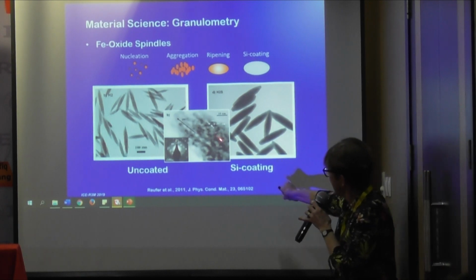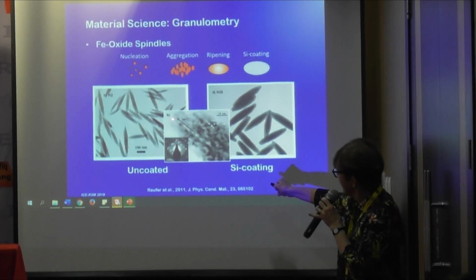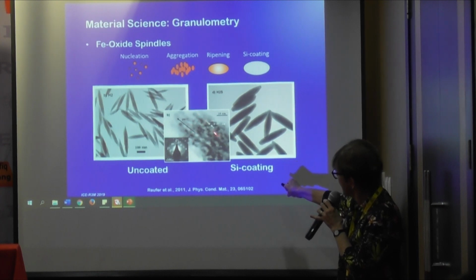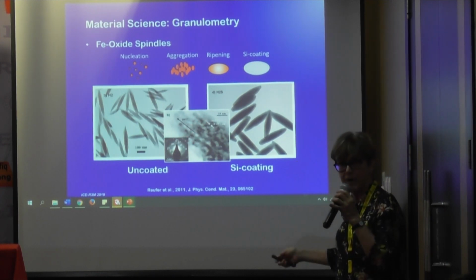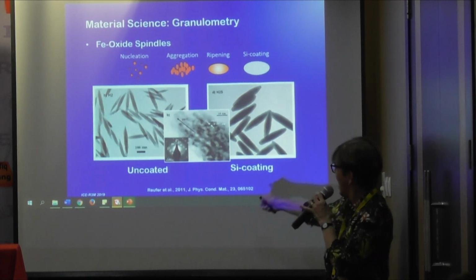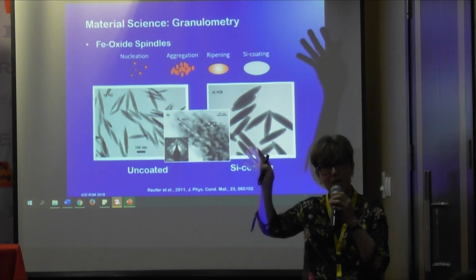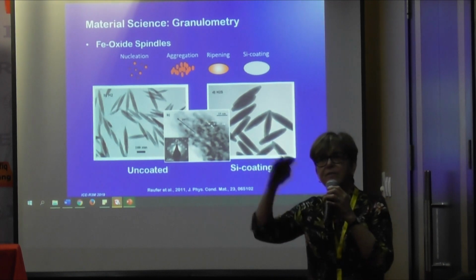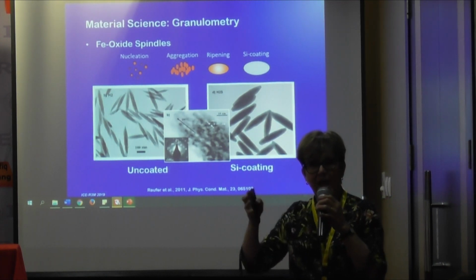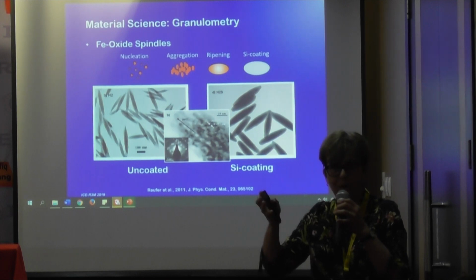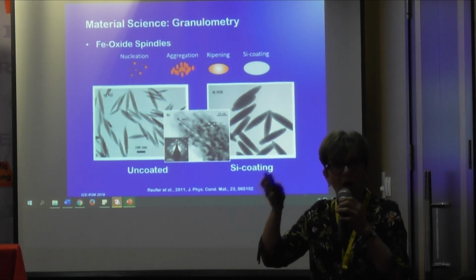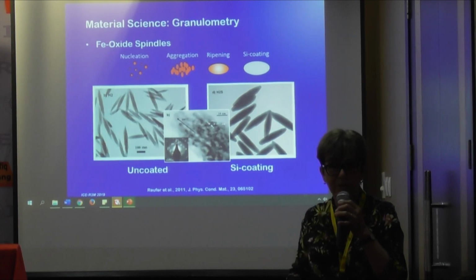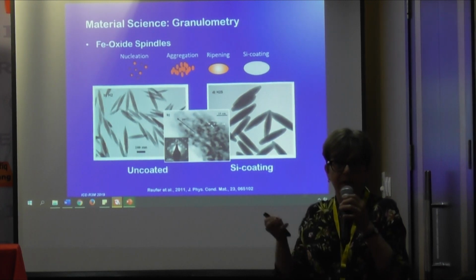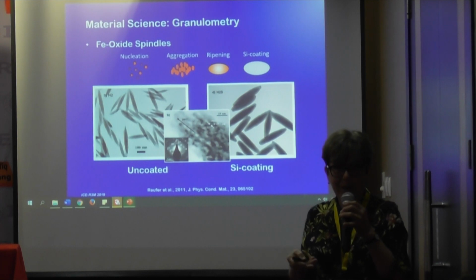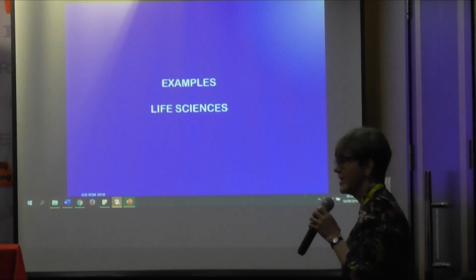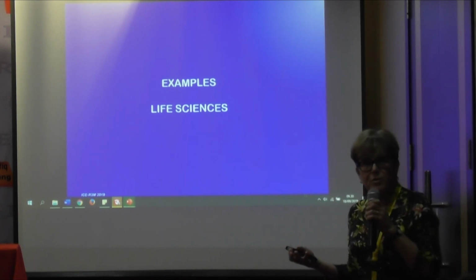Next. What you can see from this high resolution TEM picture is, yes, you have hematite, and if I go from this point to this point to this point, I get the same diffraction pattern. So all these little islands of hematite all have the same orientation, but there's enough distance between them so that it's a series of superparamagnetic grains. So grains on the order of 5 to 6 nanometers, with enough space between them that they preserve their superparamagnetic behavior. Okay, next. So just some examples from material science.